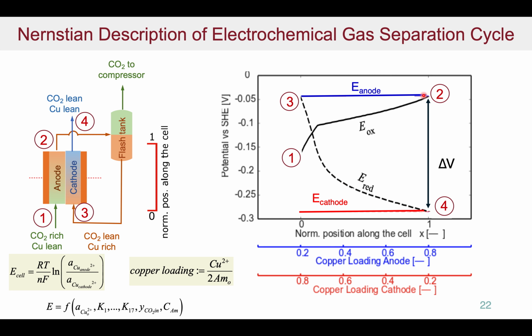The particular potential applied would not follow these curves. It would just be a constant potential. You apply constant potential across the electrodes, along the whole position itself. So what we immediately see are some inefficiencies associated with the fact that the electrodes are at constant potential rather than varying potential depending on the concentrations.